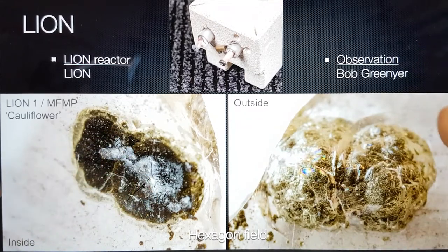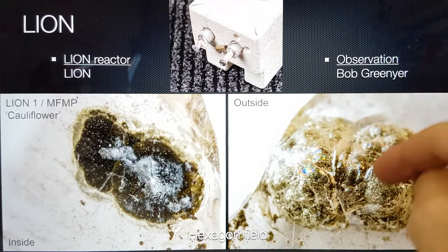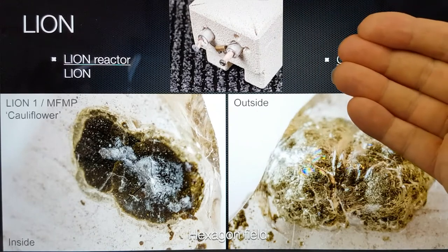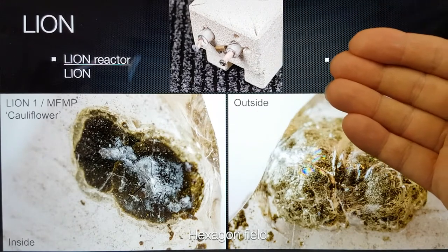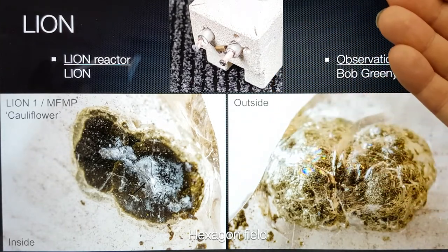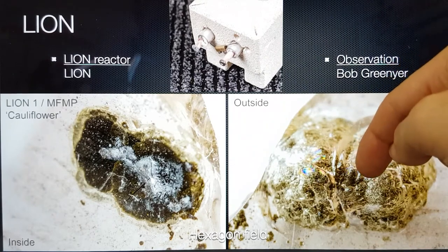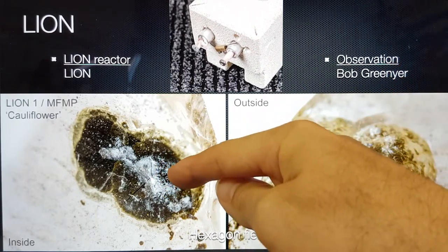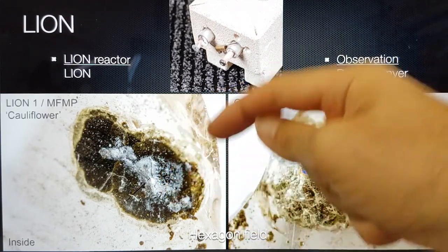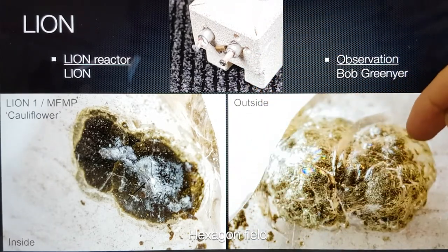Now, what do we know about quartz and discoloration of quartz? Well, if you want to change the color of quartz, you heat it up to about 600, 650 degrees C, and then you expose it to X-rays or gamma. They often use cobalt 60 sources. And this can cause changes in the color of the quartz. So this may not just be transmutation. It may not even be transmutation. And I've discussed this before, but I'm now giving you the specific overall context of how this discoloration can have occurred.